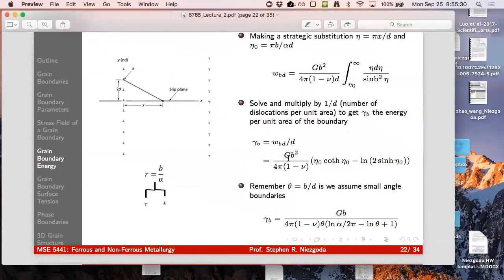I don't like thinking about general grain boundaries in terms of the strain, because I think in terms of the strain field of the dislocations, because it really only makes sense for low angle grain boundaries where you've got nice planar arrays of dislocations. As soon as you have a general high angle grain boundary, thinking about the individual dislocation structure of that grain boundary doesn't make sense anymore.